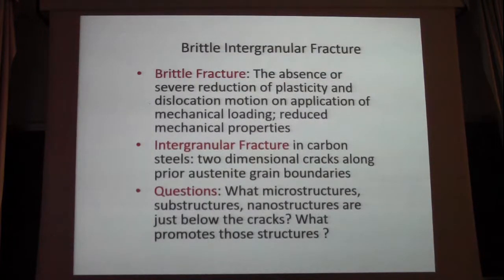So, brittle fracture is the absence or severe reduction of plasticity and dislocation motion on application of mechanical loading. And so you get severely reduced mechanical properties. Intergranular fracture in carbon steels: two-dimensional cracks along prior austenite grain boundaries. Questions: what microstructures, substructures, nanostructures are just below the cracks? What promotes these structures? These are ongoing questions.